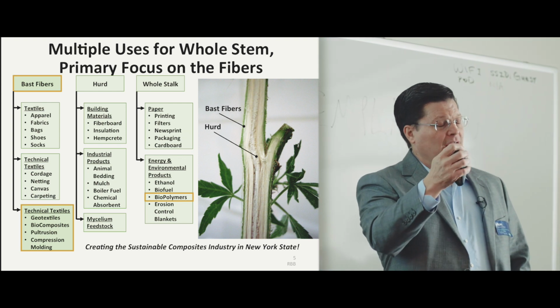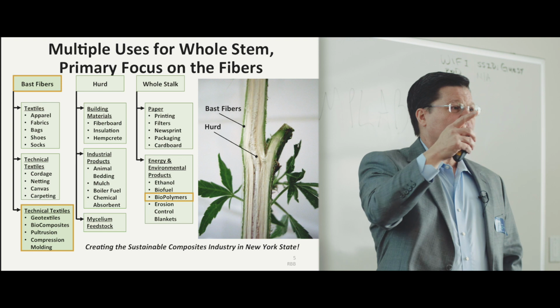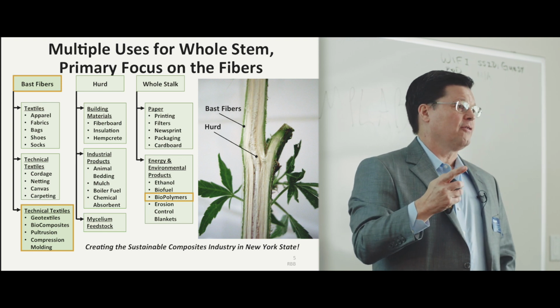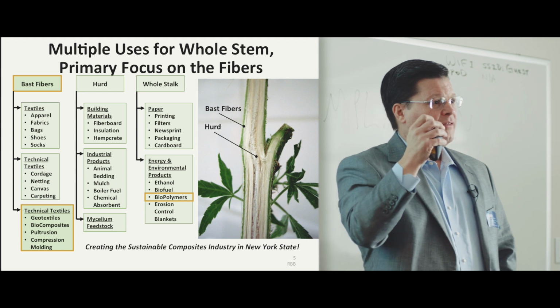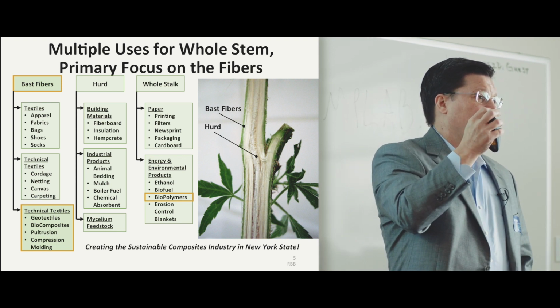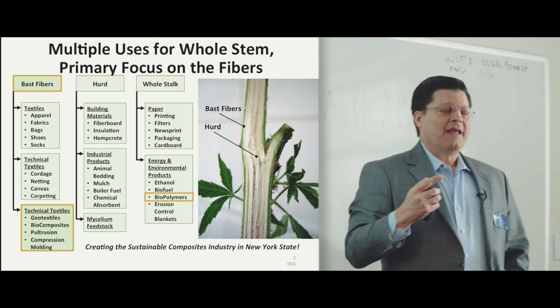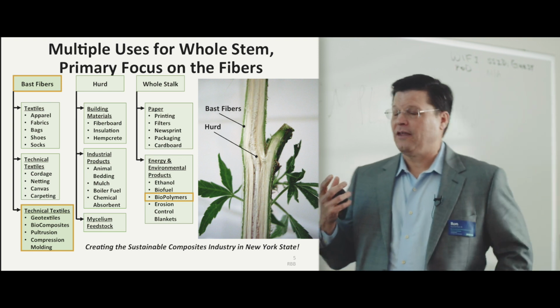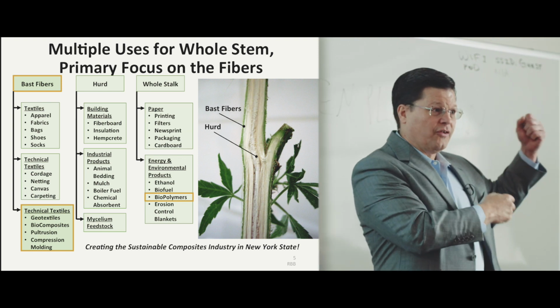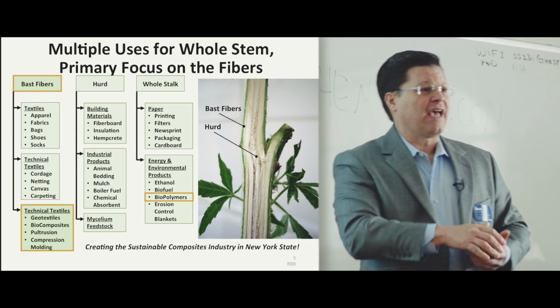And what you have to understand is when you look at those fibers, you look at all the things coming off, those aren't really the fibers that are giving you the strength. Okay? It's these cellulosic fibers that are in there that are really small. And they're covered by lignins and pectins and all these other things that a lot of people are taking away. And the reason you're taking those away is because the cellulose is where the strength is and where the great properties are. And these other things just kind of weaken it down.